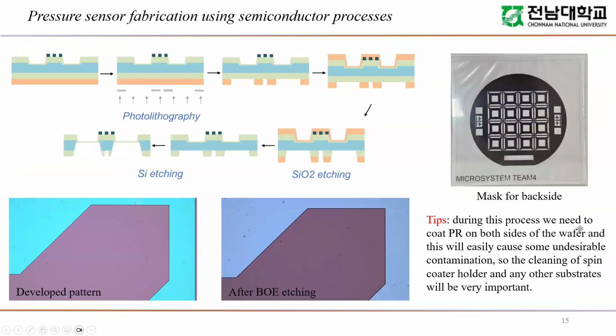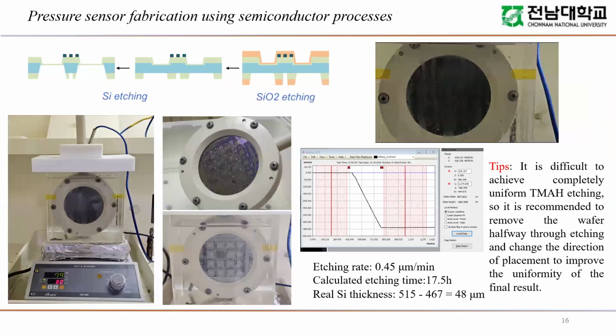And lastly, we did the backside etching. We put PR on both sides and do the photolithography process for the backside pattern for the diaphragm. During this process, we need to coat PR on both sides of the wafer, and this will easily cause some undesirable contamination. So cleaning the spin coater holder and any other substrate will be very important.